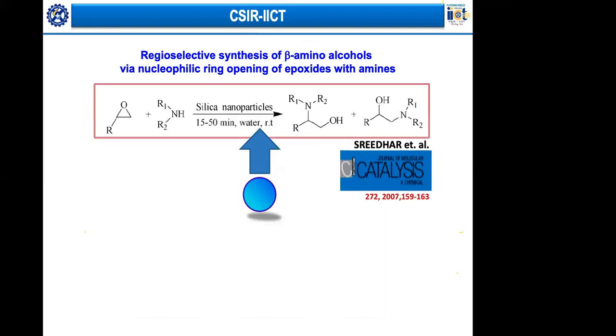So coming to my work, initially we started with silica nanoparticles using the Stöber method that I have already mentioned, where we can synthesize these silica nanoparticles of uniform size and uniform shape by taking the precursor ratios appropriately. This is an interesting work for me because this regioselective synthesis of beta amino alcohols is a very well-known reaction. But people have used harsh conditions. Here, we just used silica nanoparticles, and at room temperature, within 15 to 50 minutes, we were able to get the desired products of our interest.